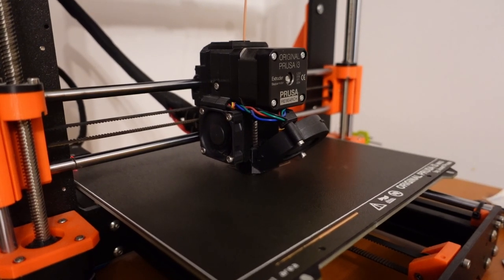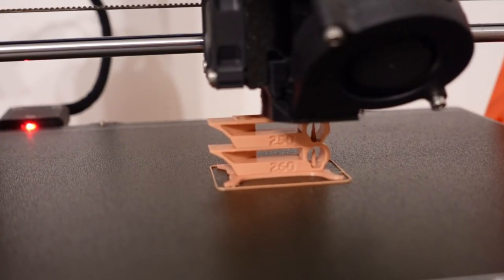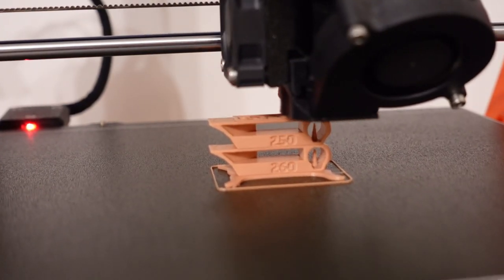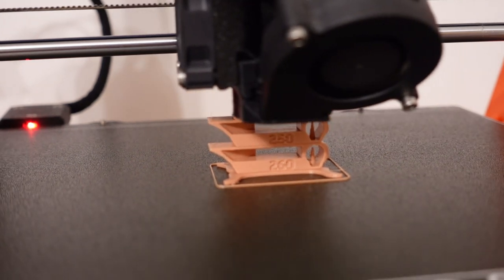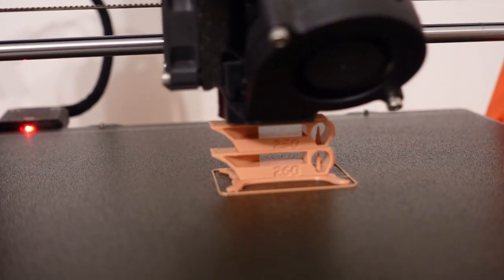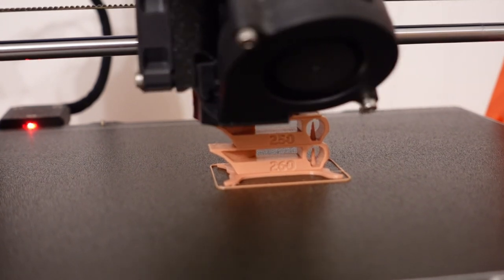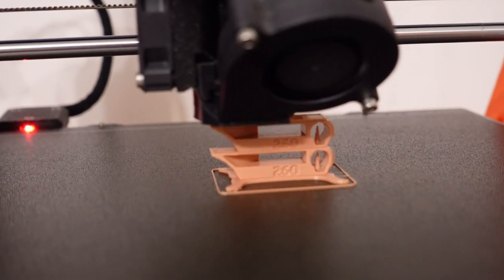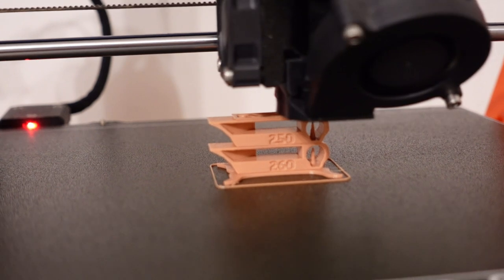I'm printing on an open printer, and immediately after printing I will place it back into the resealable bag with some silica gel inside. It's finishing the second element at 250 degrees Celsius, and only at 260 I can see very minimal stringing. At 250 it is completely clean. You know, stringing is the first sign that it may have to be dried or something like that. But in this case it is almost completely dry.